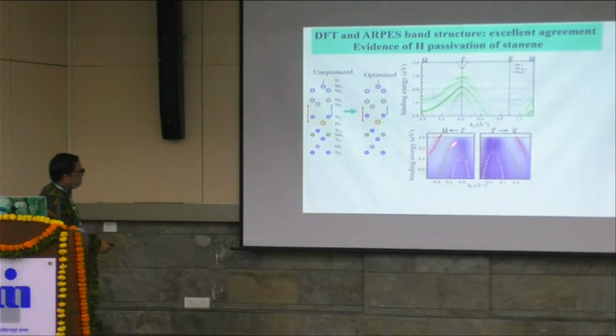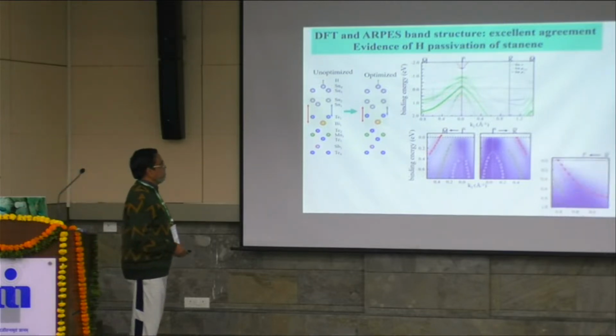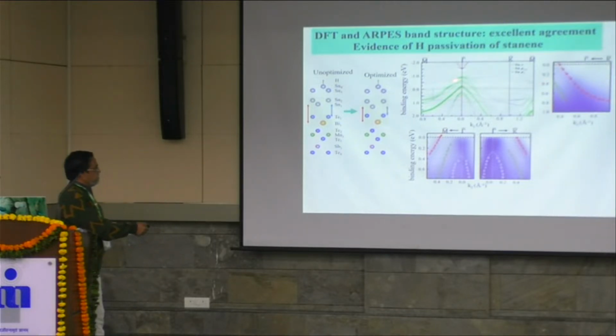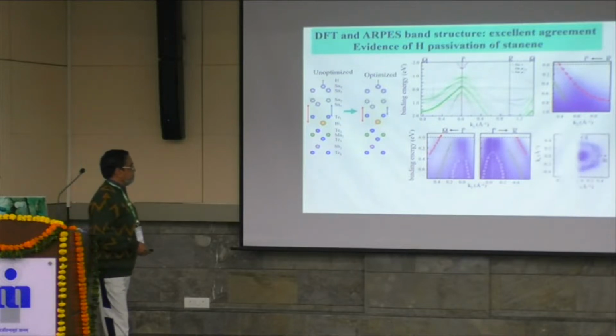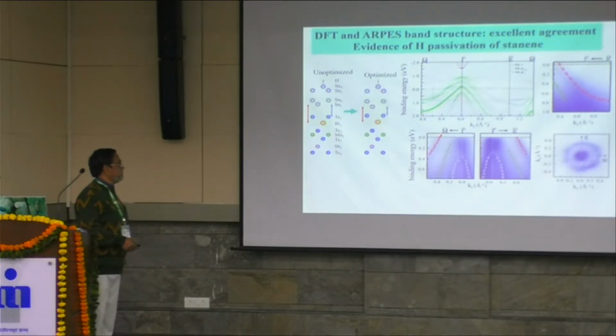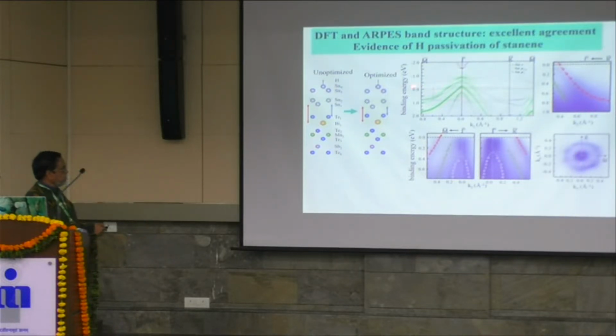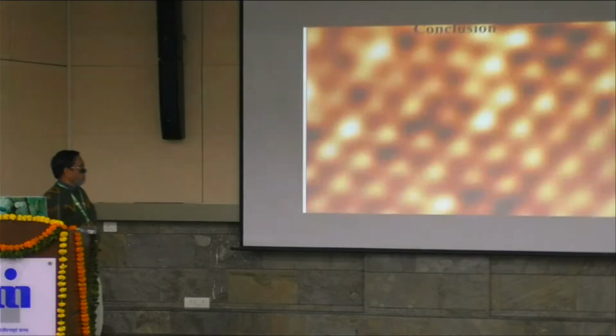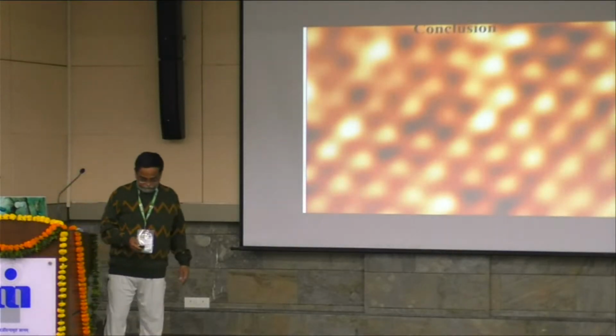These are the experimental bands. This is the gamma point. This is the inner hole band. This is the outer hole band. So you get extremely good agreement. And also along this direction here, we could get good agreement. So from that, this is the Fermi surface related to these two bands crossing the Fermi level. So we can conclude that it is stanene.